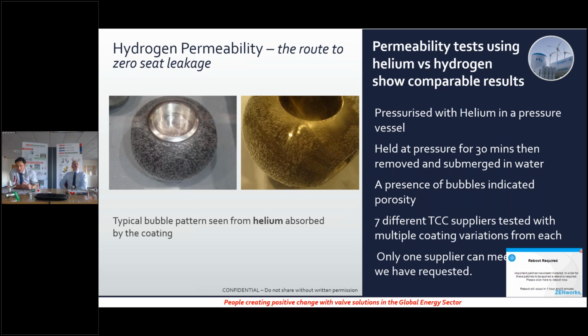But actually, the real magic, and the bit I want to share with you today, is in the tungsten carbide coating itself. Now, tungsten carbide coating is used to create a nice hard wearing surface, so the components can operate against each other without causing any issues. But porosity within the coating, we've learned, is the difference between a standard metal seated valve and a zero leakage reliable valve. So we set out, recognizing this, and we work with various tungsten carbide suppliers, well-known manufacturers around the world, to create a non-porous coating.